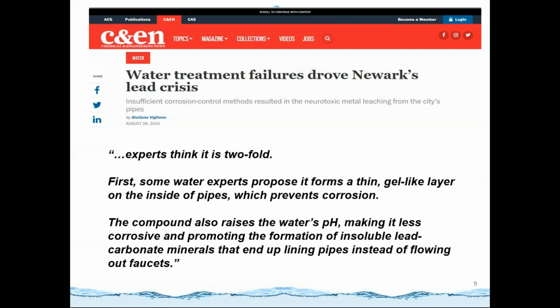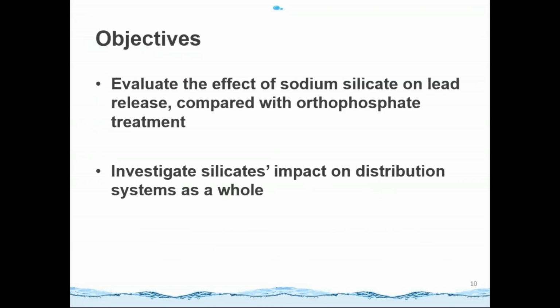Another hypothesis is that when we dose sodium silicate, it will increase the water pH, which can decrease the solubility of lead carbonate at most conditions. So the objective of my study is to evaluate the effect of sodium silicate on lead release, and we compare the data with the orthophosphate treated system, which is the well-established corrosion control strategy. We also investigate the silicate's impact on the distribution system as a whole.